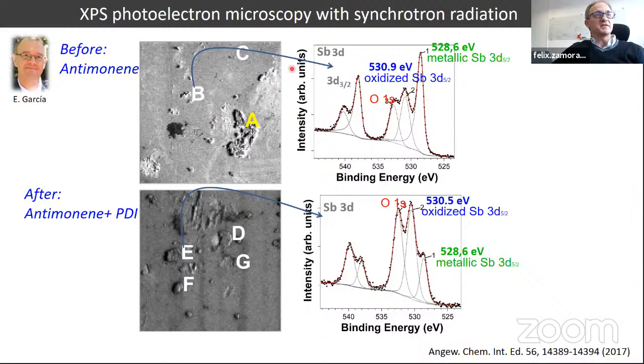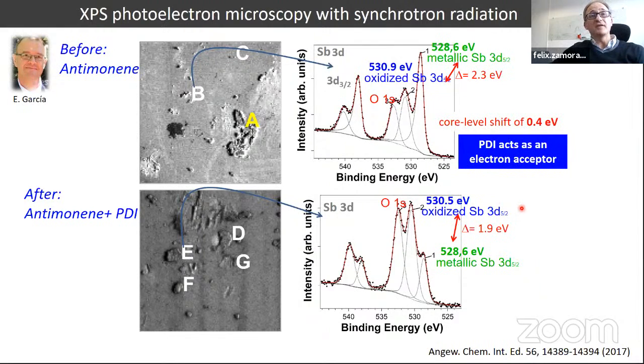Then we treat the sample with our molecule, and we collect the same spectrum again after this treatment, and we observe, on one hand, a kind of shift in the peaks. If you analyze properly, you can observe that between the two samples we have a core level shift of about 0.4 electron volts, which is telling us that the perylene diimide molecule is acting as an electron acceptor, which is the experiment that we were looking for. So we get this donor-acceptor interaction between the antimony and the perylene diimide molecule.